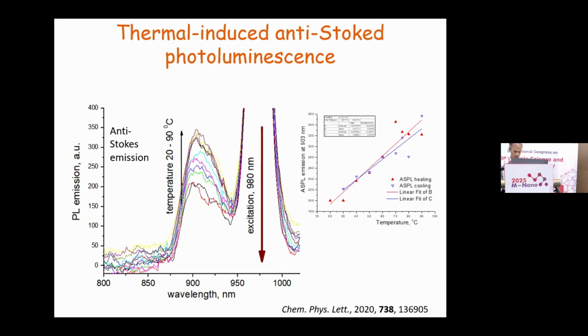A specific property of Anti-Kasha emission is that it is dependent on temperature, because higher temperatures improve population of the hot band. That means that more electrons can fill the hot band, and we can realize anti-Stokes emission with better efficiency. Here you can see the increase of anti-Stokes emission intensity dependent on the temperature. The higher temperature yields higher intensities. And here you can see the integral emission dependent on the temperature, which is a linear function when we increase temperature, and when we decrease temperature, these curves are almost similar.